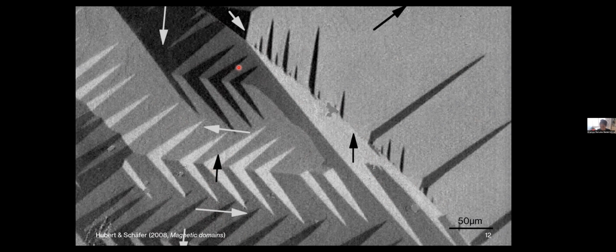So what we propose is, when we're computing hysteresis, we need to do a non-linear stability analysis in the presence of an instability or a large localized disturbance like that of a needle domain. Because when you're applying an external field across a microstructure such as this, these needle domains grow in size, and at a specific value, they completely reverse the net magnetization of the material. And the growth of this needle domain experiences a certain resistance, which is determined by the delicate interplay between material constants. And that is something that we propose to investigate.